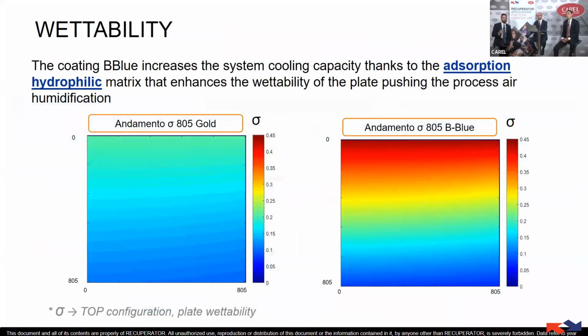Now let's focus a little bit more on this coating. This coating is special because we've seen that it's hydrophilic and also absorption. It's able to retain the water on the surface. Then we can increase the wettability. We can create an even film of water on the whole surface, decreasing the whole temperature of the system. In this way we increase the cooling capacity. In this picture we show the wettability in terms of sigma of the plate. With the gold, we have a wettability of a value that is half of the wettability of the blue, because of the hydrophilic and absorption characteristics.